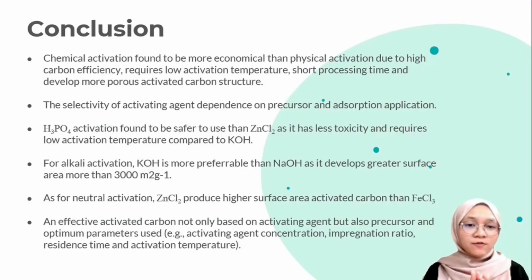Last but not least, for the conclusion, chemical activation is found to be more economical than physical activation due to the high carbon efficiency, low activation temperature requirement, short processing time, and development of a more porous activated carbon structure. The selectivity of the activating agent depends on the precursor and adsorption application. Phosphoric acid activation is found to be safer to use than zinc chloride as it has less toxicity and requires a low activation temperature compared to potassium hydroxide.